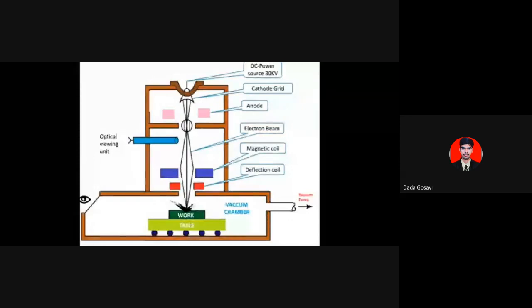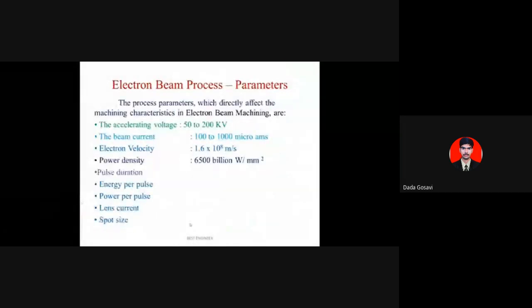These are the important process parameters: accelerating voltage, beam current, electron velocity, power density, pulse duration, energy per pulse, power per pulse, lens current, and spot size. We maintain the accelerating voltage around 50 to 200 kilovolts. The current is 100 to 1000 microamps. Velocity is 1.6 times 10 to the power 8 meters per second, which is about half the velocity of light. The power density is 6,500 billion watts per square millimeter.